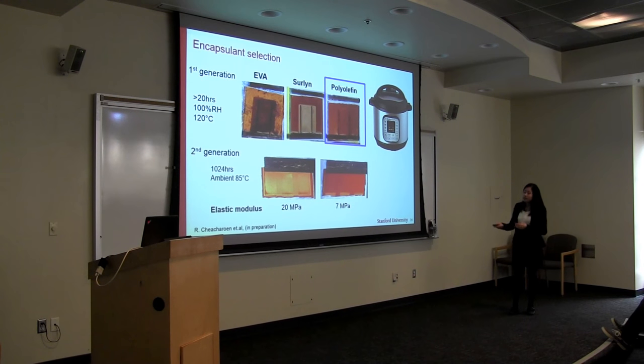So I further studied which polyolefin to use. I compared two of them with two different elastic moduli. I found that the one with the higher elastic modulus delaminates just like Surlyn, so it's still too stiff. So we need something like 7 megapascal here, so that it keeps the active area, the protected active area, intact. So I picked this for my further damp heat test.